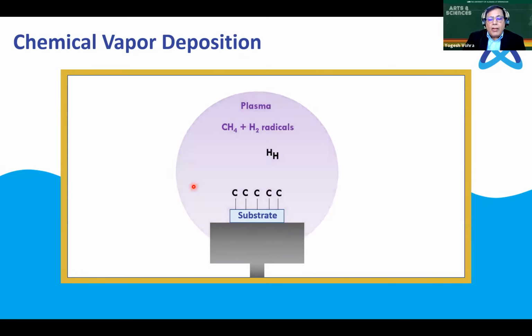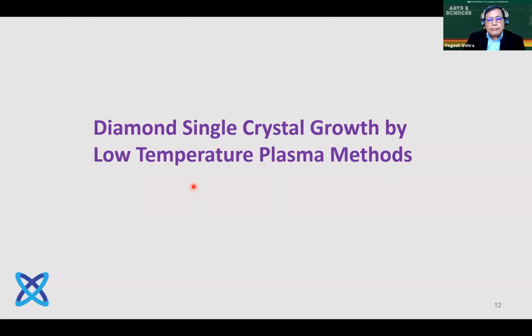And this process then can be repeated again, and the cycle continues till you deposit a carbon-based material, mostly from our point of view, a carbon which is bonded in a specific way, like four-fold bonding, like a diamond crystal. Okay, so with that brief introduction of how the diamond crystal grows on an existing diamond substrate, we are going to move on to some of the actual